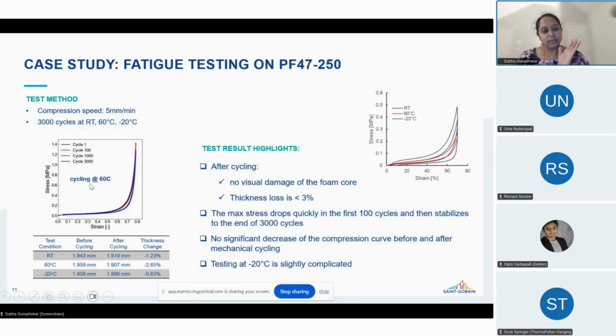That's what this graph is showing. And then this is a summary of all the three different temperatures. At different temperatures and after 3000 cycles, you can see there's not been much material loss. The foam is still intact, no visual damage. The thickness loss was less than 3%. And then the stress drop was stabilized after the first 100 cycles. So there was no significant pressure or stress loss, irrespective of the number of cycles here.